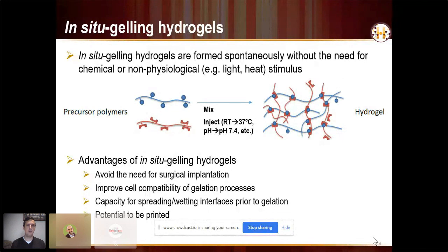So the idea behind these is that we start with precursor polymers. In our case, we look at covalently cross-linked gels, although there's a variety of physically cross-linked in situ gelling hydrogels that are also available that, based on physiological temperature or pH or other local stimuli can gel in situ in the body. But what we do is we functionalize different polymer precursors with different functional groups. So when we mix them together, those functional groups can react under physiological conditions and form a gel.